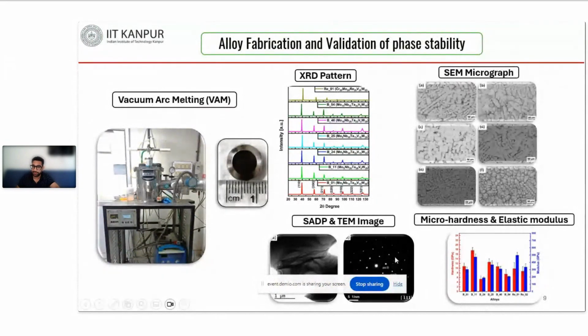After validating that this alloy is showing a single phase structure, we tested its mechanical properties and found that the micro hardness and the elastic modulus are showing better properties in comparison to even the equiatomic counterpart. So we can say that obviously the non-equiatomic alloy is showing better phase stability, and when we tested its mechanical properties, it showed better mechanical properties than its equiatomic counterpart.